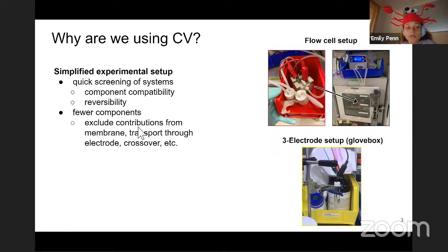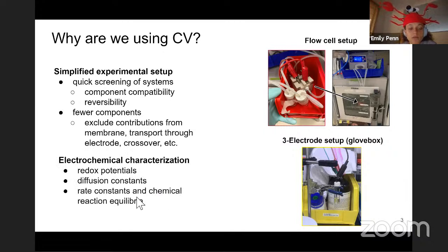So in the flow cell, we have contributions from the membrane interface, transport through the porous electrodes. We can also have crossover between the positive and negative side of the battery. So testing in this 3 electrode setup allows us to exclude those contributions and look more closely at what's going on with the electrochemistry of the quinone. Also, we're able to do more quantitative electrochemical characterization. So using CV, we can determine redox potentials for these different molecules. We can also look at diffusion constants in different scenarios. And we can also determine rate constants and chemical reaction equilibria for coupled chemical reactions.